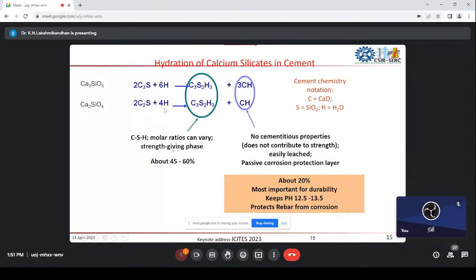The remainder after the reaction is calcium hydroxide. Calcium hydroxide is a very key chemical property which makes the concrete durable. It maintains the alkalinity, with pH around 12.5 to 13.5. This is the key factor which protects the rebar from corrosion. As long as the concrete is in the alkaline state, it can protect the steel. When it becomes acidic, the steel starts to corrode, and it is accelerated corrosion, and it quickly loses its properties.